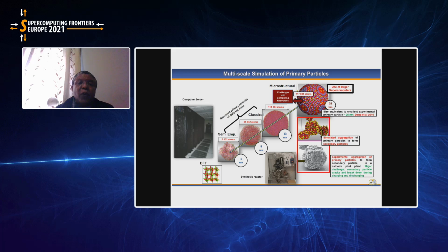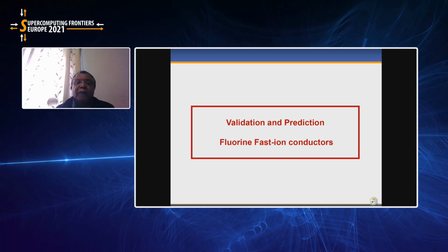where the density functional methods work and where the empirical methods work, like linear scaling methods that enable us to find particles that are found in cathode materials, and these increase in size to various nanometers, where we have 20,000 atoms, and then 100,000 atoms up to 1 million atoms. Now, those primary particles can be put together to form secondary particles, and these will sort of simulate what we actually find inside the reactor, where we have secondary particles consisting of a number of primary particles.